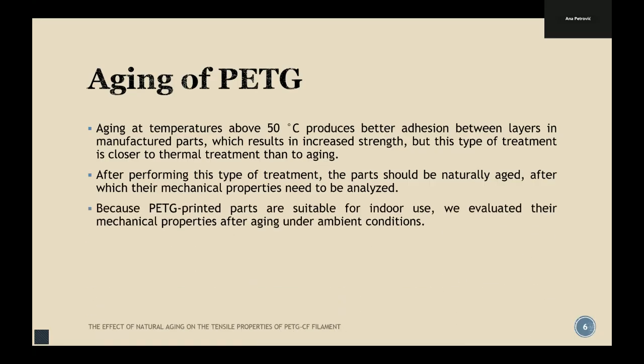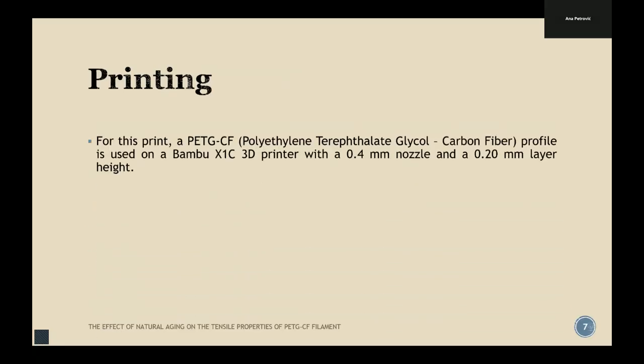Because PETG printed parts are suitable for indoor use, we evaluated their mechanical properties after aging under ambient conditions. We know that exposure to UV light or something like that will lead to degrading or decreasing of the parameters, so we say that PETG can generally be used for indoor applications.